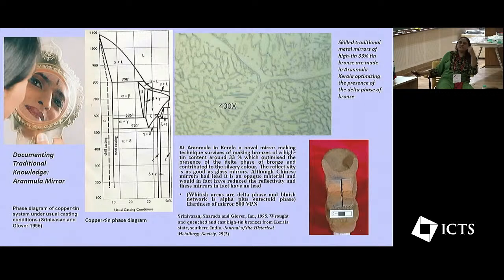So as I was mentioning, the earlier sample that I showed you was of a leaded bronze, and there the tin content would have been typically less than about 15% tin, because that is when the alpha solid solution of tin in copper forms, as you see here, this symbol alpha. So up to about 15%, the tin is actually soluble in copper, so it forms a solid solution. But what happens when you keep adding tin to copper? It actually becomes more and more brittle at higher concentrations of tin.